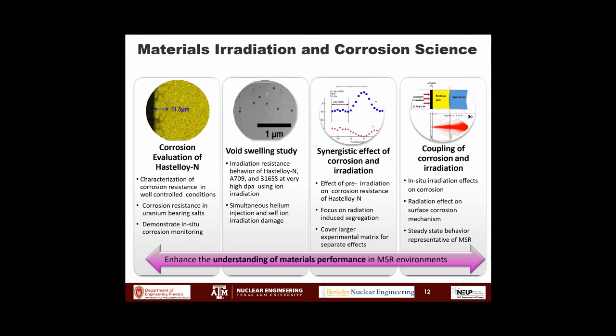Another large thrust of the project is material irradiation and corrosion science. As we know, the reactor system needs materials, and it's important to understand how those materials interact with and are affected by the coolant and the radiation field. In most of our studies here, we're focusing on what was identified as a promising candidate from the times of the MSRE, basically alloy N, which is the material we are currently studying. In the studies that we carry out, we mix the strengths of the Texas A&M Ion Irradiation Lab and the University of Wisconsin at Madison Corrosion Study Labs. We care about element loss, crack initiation, boundary segregation, precipitation, hardness changes, void swelling, and so forth. I'll dive a little into what these two groups are doing.